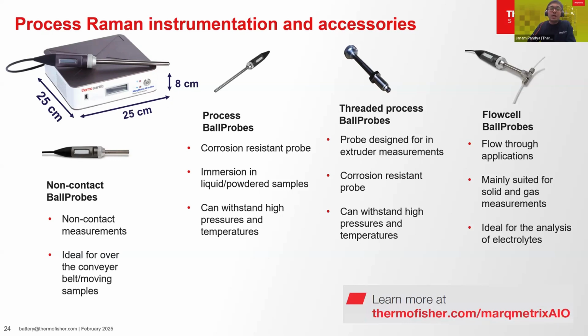The process ball probe is a contact probe manufactured using Hastelloy material, which can withstand corrosive and oxidative chemicals in the environment. It can be utilized to measure slurries, liquids, and powder samples, and can withstand high temperatures and pressures. The threaded process probe is specifically designed to fit in the extruder, either on the die end or mid-barrel. It can also withstand high temperatures and pressure, and is commonly utilized to monitor extruded uniformity or to monitor reactive extrusion.